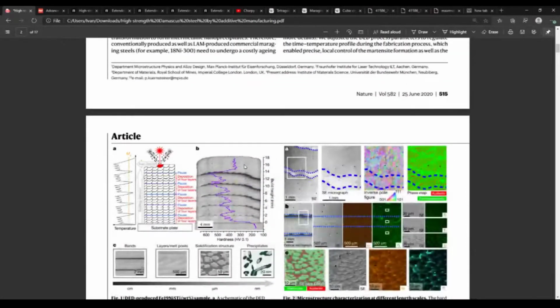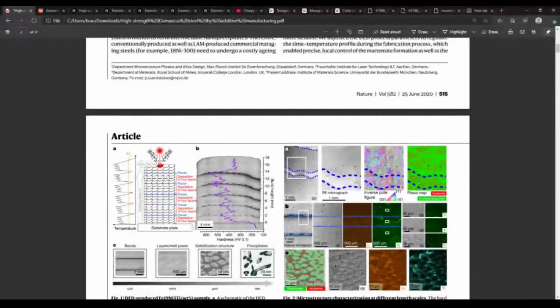So they don't discuss at any point problems with the wear? They don't. In this paper, there's no discussion on the wear and tear. They just stop the machine for a set period of time for the piece to cool below the martensitic temperature, and then they go ahead. So they start and stop and let it just cool. But research papers are oddly amazing at their ability to just say, and by the way, everything that we used got destroyed while we did this research. So that's normal.